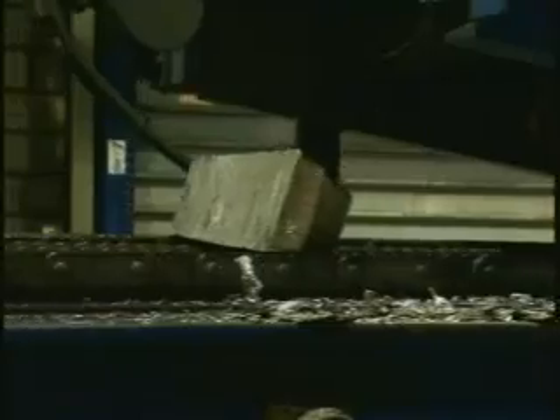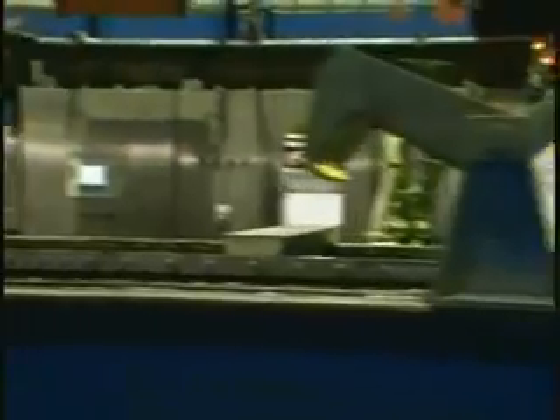After further cooling to 70 degrees Celsius, the bars are mechanically extracted from the mold at the discharge end of the casting machine. Depending on customer specifications, the bars receive a color marking, so one can see at a glance, even from a distance, what kind of alloy is involved.